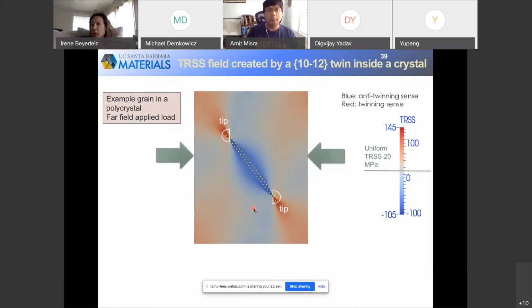That's possible in HCP materials because different slip modes have vastly different critical resolved shear stresses. Another way is just by introducing the boundary. By introducing a boundary, you disrupt the crystal orientation, which means dislocations that like to glide on one particular plane have to change their course, and there's extra energy needed to have that slip transfer across the boundary. So those are two ways to harden.